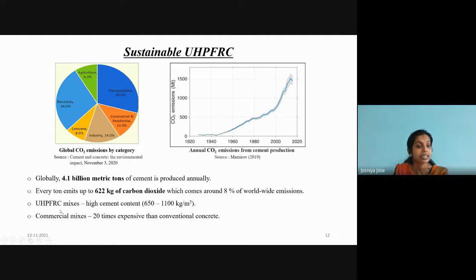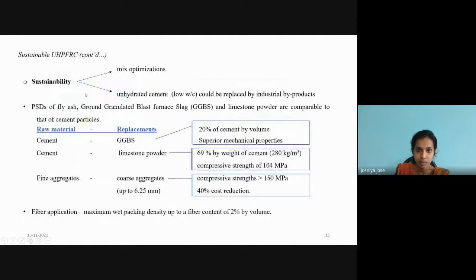Still, we know that UHP-FRC mixes require high cement content, around 1000 up to 1100 kilograms per cubic meter. And the commercial mixes, like maybe Dura or Ductal by Lafarge, are 20 times more expensive than conventional concrete. And from this figure, we can see that the concrete industry is responsible for 8% of the global carbon dioxide emission. And from the graph also, we can see that it emits around 1,500 million metric tons of carbon dioxide. So sustainability is indeed a pressing issue.